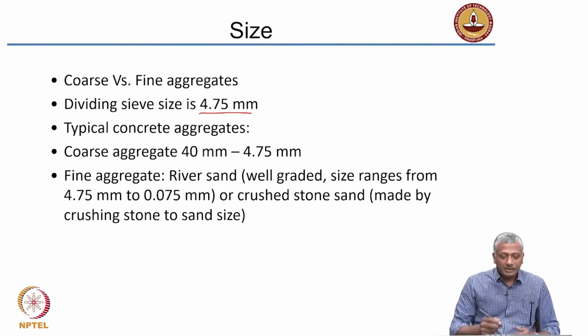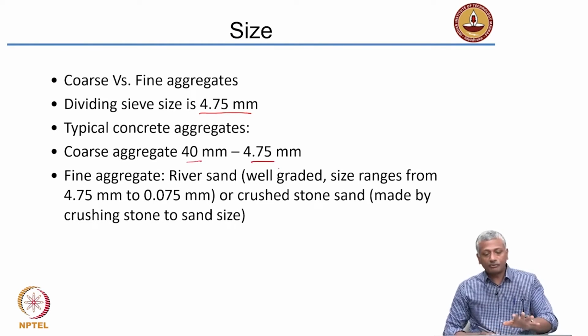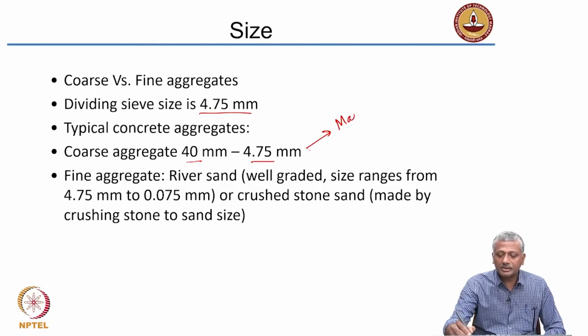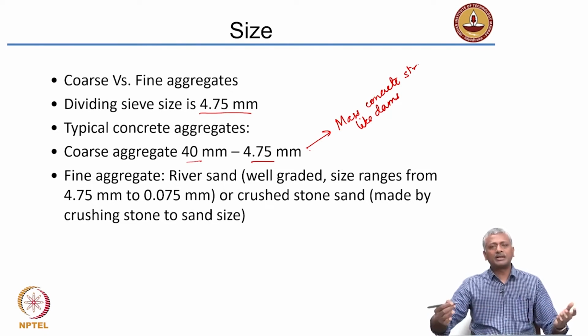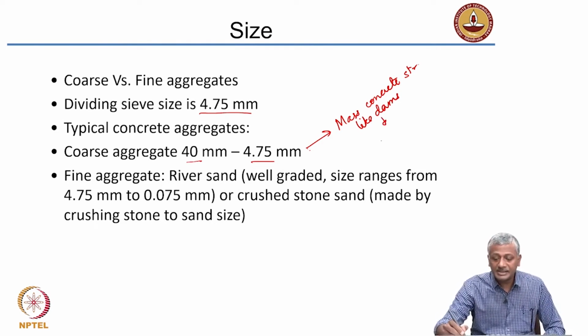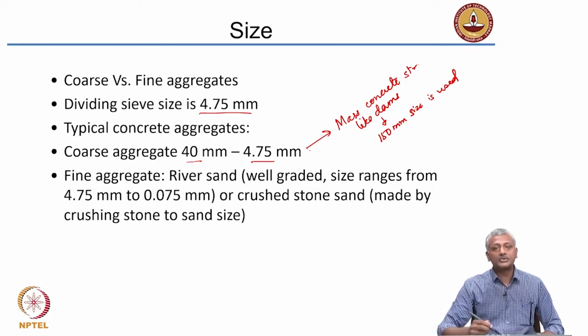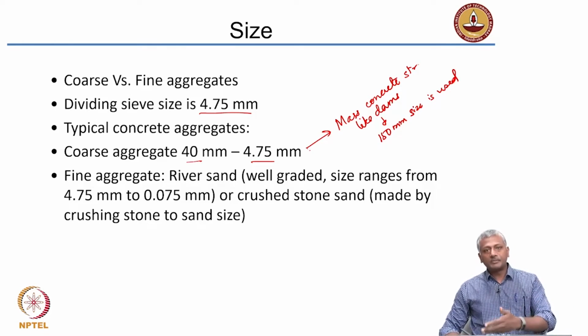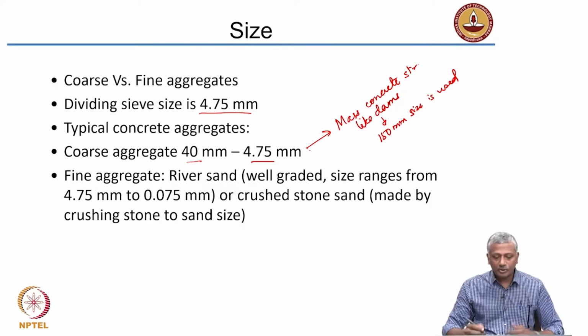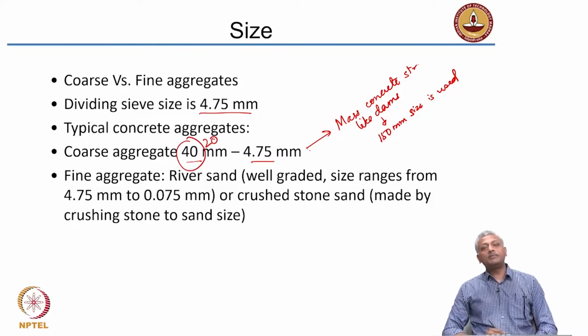Coarse aggregates typically are 40 millimeters to 4.75. Now, of course, in very large mass concrete structures like dams, where we have very large chunks of concrete to be put and not necessarily much requirement of strength from it, even 150 millimeter size aggregate is used. You can use 80 millimeters, 150 millimeters and so on. But for general purpose construction, dealing with foundations and building superstructure, we will rarely go with more than 40 millimeters. In fact, for the most part, we will be going with only 20 millimeters. We will not go much more than 20 or 25 millimeters at the most, but you can use in some instances 40 millimeters also.